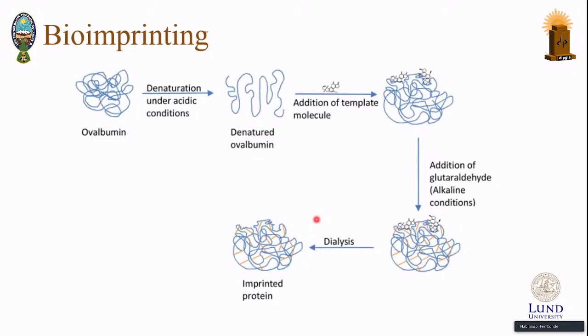One of the molecules that we are using for the biorecognition is the bioimprinting. We were using albumin and ovalbumin, but we have seen that the albumin has a lot of hydrophobic amino acids, so it's better to use ovalbumin. In the case of ovalbumin, we performed denaturation as the first step to get a denatured ovalbumin.